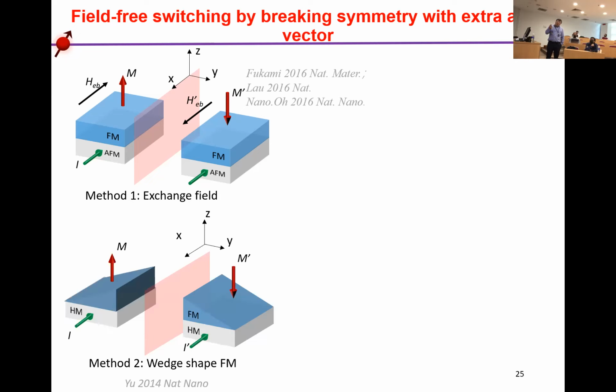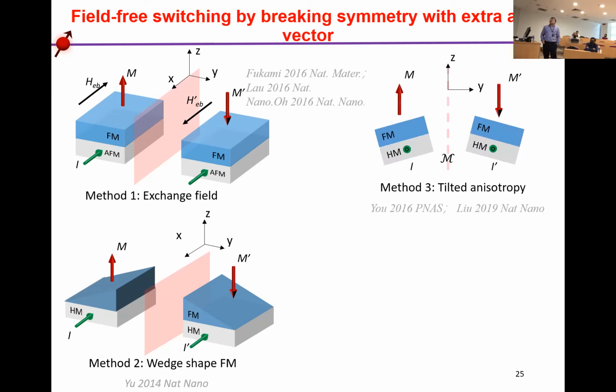And also use wedge structures. When you apply the mirror symmetry, the geometry should be changed, but it cannot change, right? So they break the mirror symmetry. So this also has been demonstrated to cause deterministic switching of the perpendicular magnetization. Another one is by using a macro fabrication method, you change the z-axis, or you tilt the magnetization directions, or you control the z-axis by the deposition or sputtering.